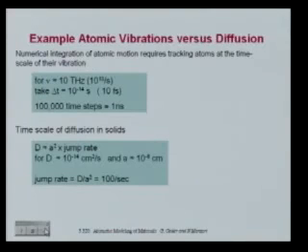So remember, you have to integrate the equations of motion. So think of an atom vibrating in some well or against another atom. You probably need at least 10 discretization steps along that one vibration. So your time step is of the order of 10 to the minus 15 seconds, 10 to the minus 14 seconds. That's the order of magnitude. For different materials and different algorithms it will be different, but that's 10 femtoseconds. So you have to do an iteration step every 10 femtoseconds. So even if you do 100,000 time steps, you still only have 1 nanosecond of time.